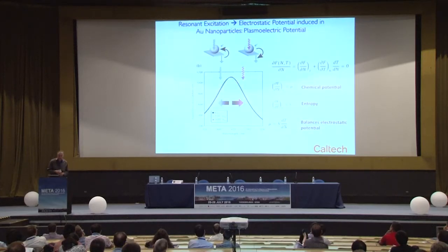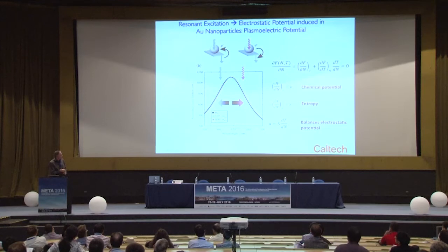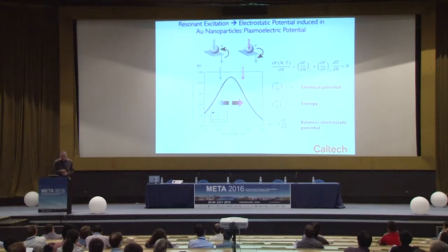What about the opposite? If we were to resonantly excite a metal particle with a narrowband excitation source like a tunable laser source, on the blue side of the resonance frequency for a neutral metal particle, what we can see actually is that that particle, from free energy considerations, can minimize its total free energy by adopting a non-neutral configuration. The way to understand this is that the increase in extinction leads to a change in the entropy and the entropic heat contribution to the free energy. And in fact, the particle will adopt a charge density different from its neutrality under uniform or broadband excitation.